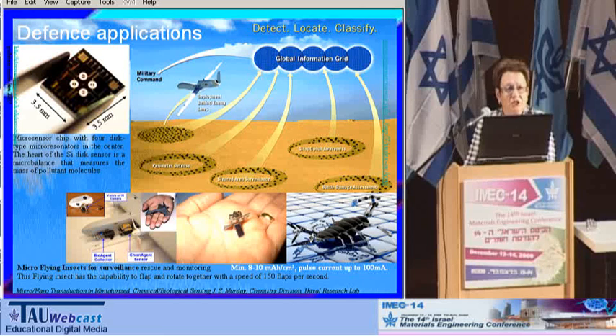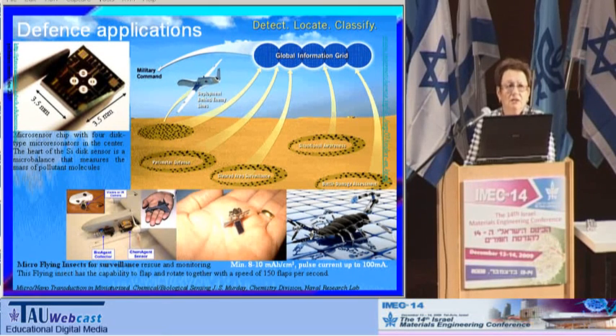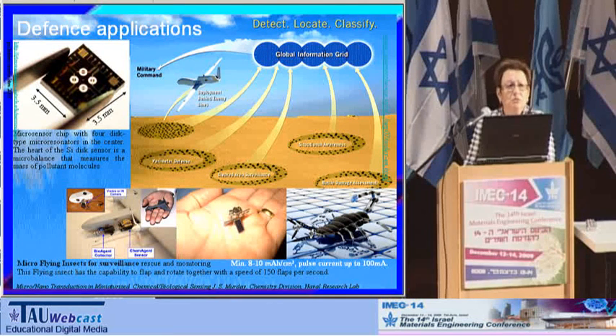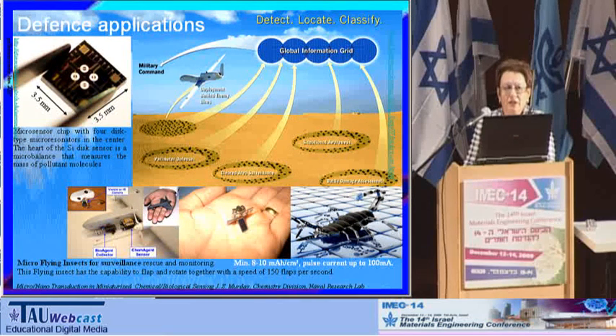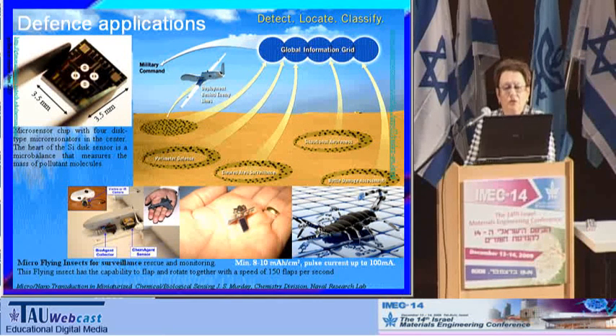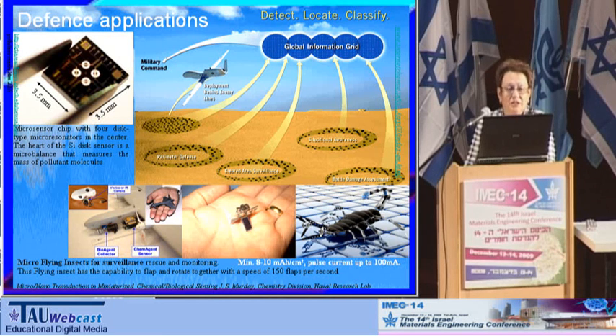For the defense applications, the microsensors can be simply deployed in an unfriendly environment, and they start to be operated by solar cells coupled with rechargeable batteries. The capacity of the rechargeable batteries should be about 10 milliampere hour per square centimeter, and these batteries must deliver pulse currents of about 10 milliampere, up to 100 milliampere. And there is no battery that can meet these very severe requirements.